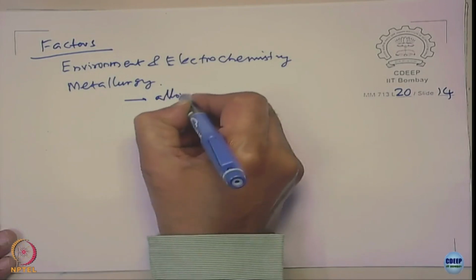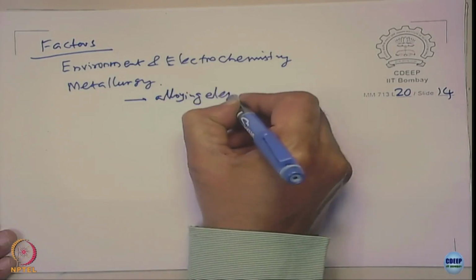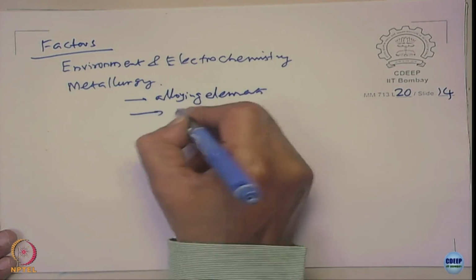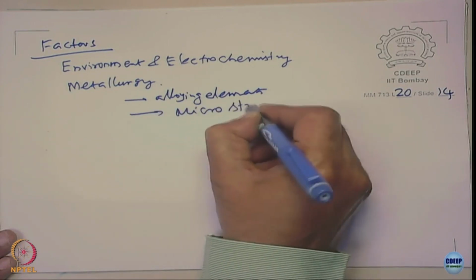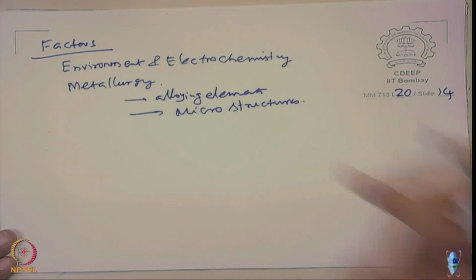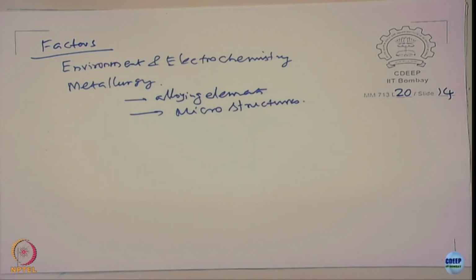We also look at the metallurgy, mostly we have seen it in relation to stainless steels, right, and how the various alloying elements affect the two parameters, pitting potential and the repassivation potential, right. We saw that various alloying elements, microstructures, do significantly affect pitting corrosion. When I say microstructures, it could be all kinds of things. It can be segregation of various phases, and we talked about cold work.